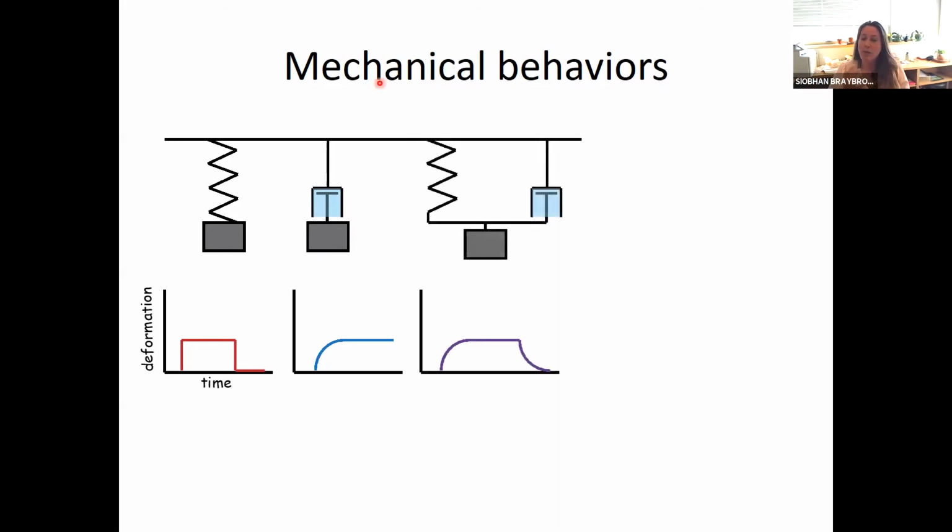But in reality, we can couple those two things together. We can get viscoelastic materials. And in a viscoelastic material, if I put a weight on it, in the beginning we could get some initial elastic deformation, but mostly we're just going to see this time-dependent relaxation because of the dashpot, because of the viscous element. But as soon as I let go of that weight again, now the spring can actually pull back the viscous element. And so you'll still get the time dependence, but the retraction force that's happening is because there's an elastic element coupled to that viscous one.